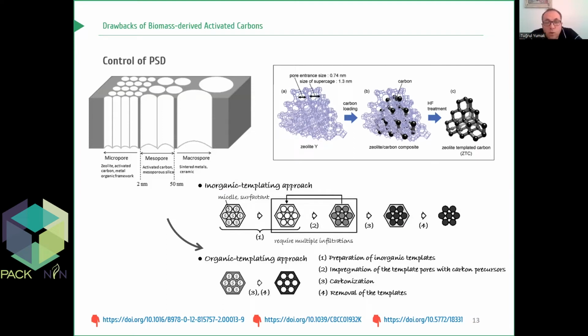Again, we expect a proper distribution of micro and mesopores for better ion transport and charge storage. But we don't know the exact number, volume, or ratio of pores that we need. So now we are playing with the experimental parameters to find out the best one.